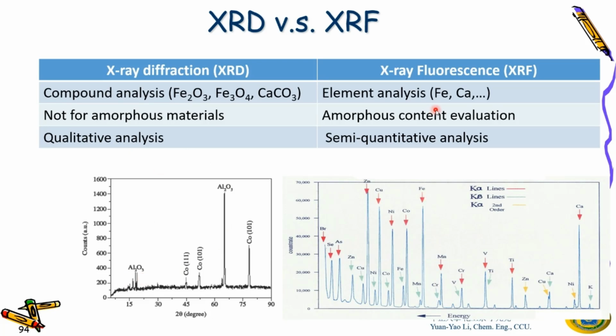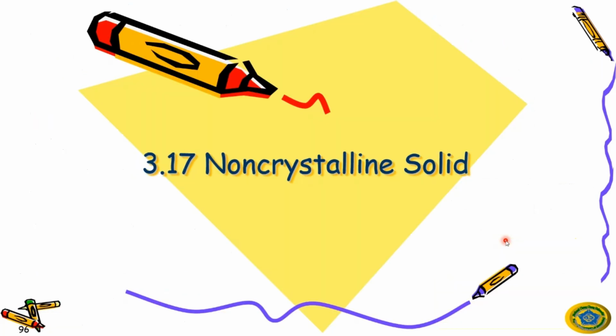And another tool I showed you last week is X-ray fluorescence, XRF. XRF is for element analysis. So if you put this oxide to the XRF, the XRF will only tell you, wow, this substance only has the elements of iron and oxygen. It doesn't tell you this material is iron oxide. It cannot tell you this is Fe2O3 or Fe3O4. But XRD can tell you. Okay, but the good thing for XRF is that you can have the amorphous content evaluation. That means it can tell you, do you have oxygen, you have iron. Okay. So this is the summary. Okay.